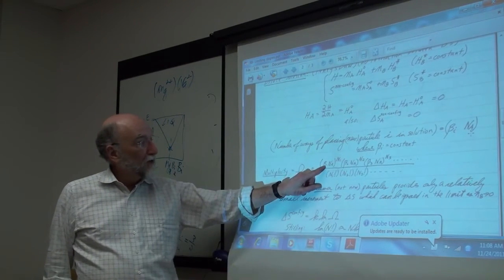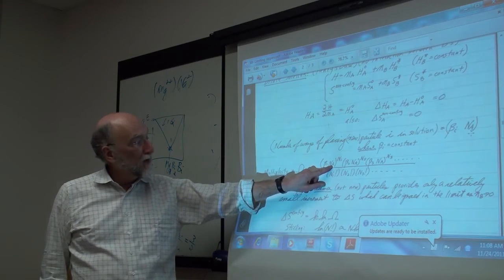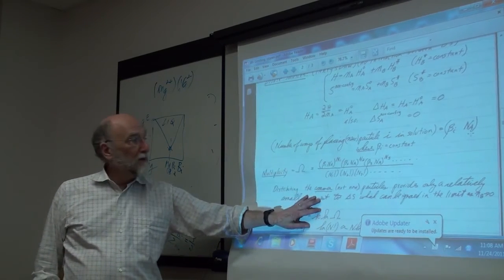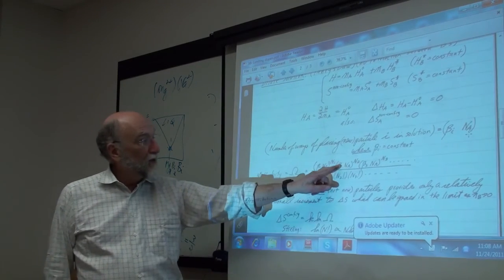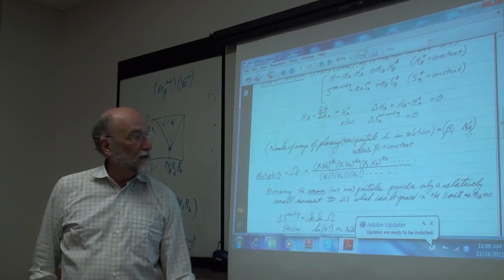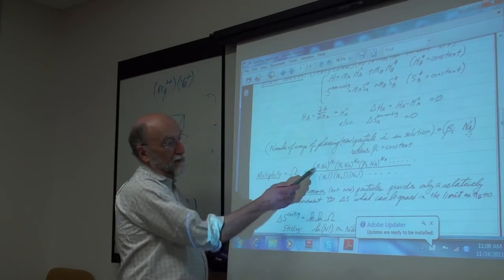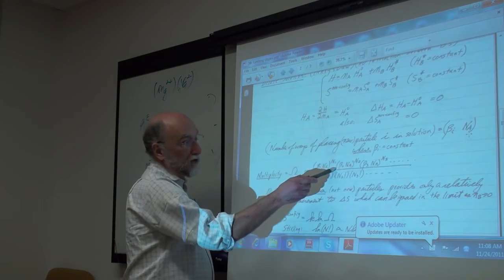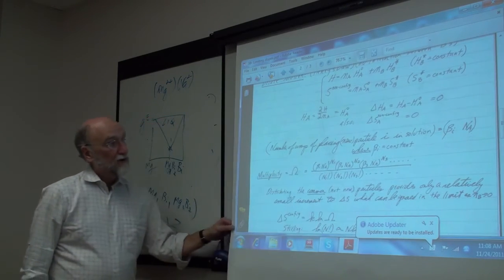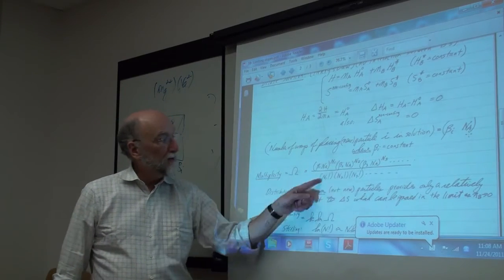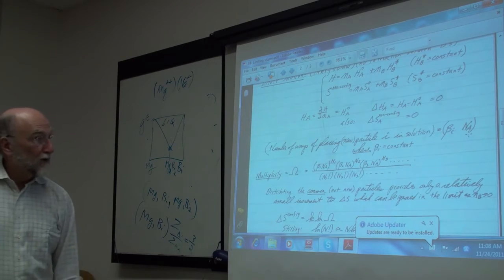Every number 1 particle can go in beta 1 Na ways, and there are N1 of them. The number 2 particle can go in beta 2 Na ways, and there are N2 of them. And so on. So this is the number of ways of putting the 1 particles in, the 2 particles in, the 3 particles in. And then the particles, of course, the 1, 2 and 3 particles are independent, so you've got to divide by that. So this is your infinite dilution multiplicity.